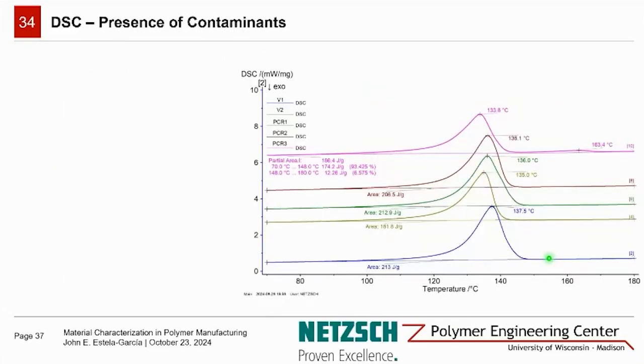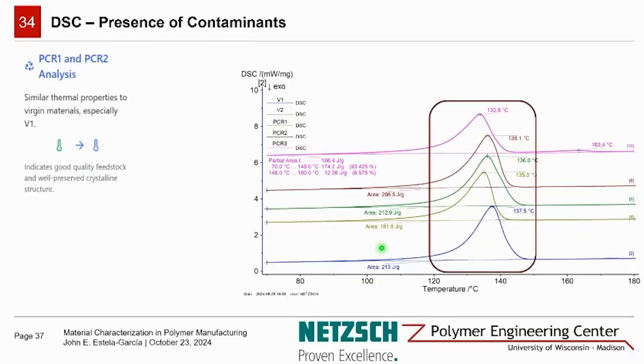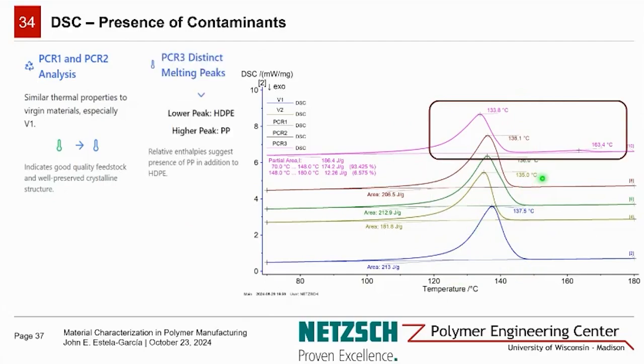So we turn our attention to DSC. And our DSC analysis reveals the composition and quality of our recycled materials. PCR1 and PCR2 are demonstrating thermal properties that are similar to virgin materials, particularly virgin 1. This suggests high quality feedstock and well-preserved crystalline structures, indicating that these recycled materials should process similarly to our virgin HDPE. However, PCR3 represents a more complex picture.